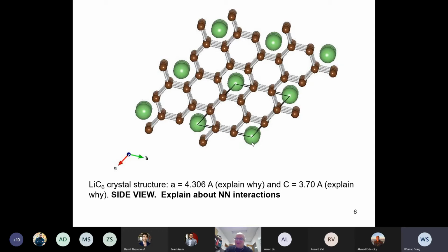Hi, Jeff. Does this apply to both the natural graphite and the artificial graphite, the 2 types of graphite, AB, AB, and ABC, ABC? Natural graphite is mostly AB, AB, but sometimes in natural graphite you will find a small component of ABC, ABC. Artificial graphite is almost always primarily AB, AB. Okay, thank you.